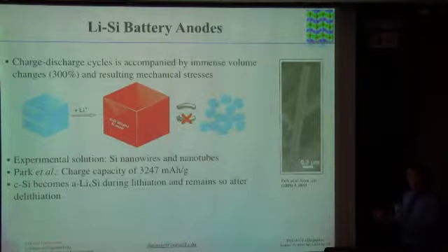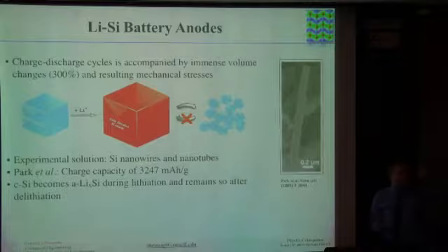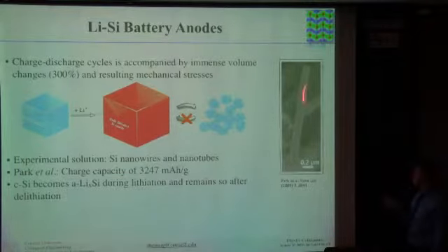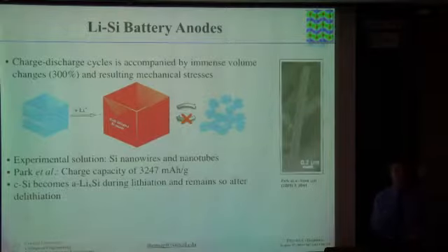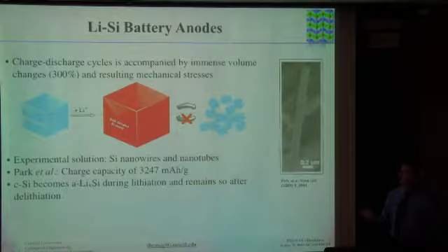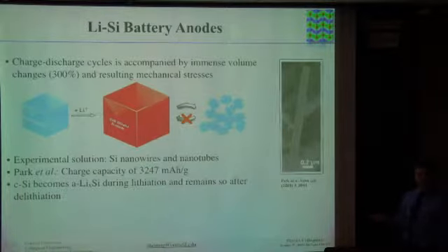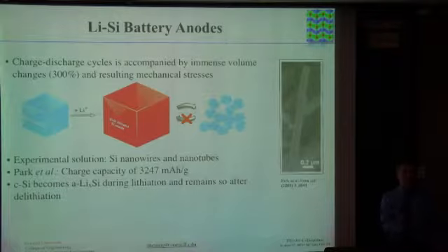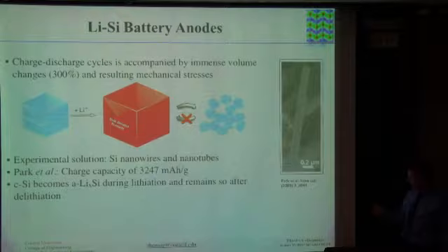So there's actually a way around. People have figured that out over the last decade, that if you go to nano structures for silicon, it doesn't turn into a powder. If you go to nano wires or nano cylinders of silicon, you can actually lithiate them and get about the right amount of lithium in there, 4 lithiums per silicon. It swells, but it doesn't fracture and break up. So there are currently various companies which are making silicon nanowires and using them as a battery electrode material. And with some luck, they can figure out the engineering feats and have commercial batteries, somewhat higher capacity.